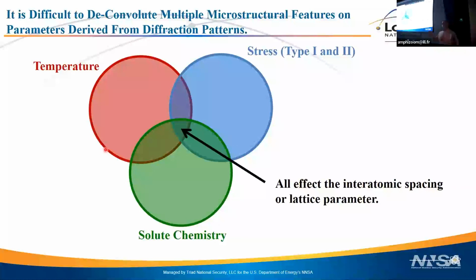There are macroscopic stress fields, which are usually referred to as type 1. And there are intergranular stress fields, which are usually referred to as type 2. Both of those will affect the lattice parameter. And finally, one we don't always think about, but we should, is solute chemistry, right? If you're looking at Ti-6-4, where the vanadium is in Ti-6-4 affects what the lattice parameter is.